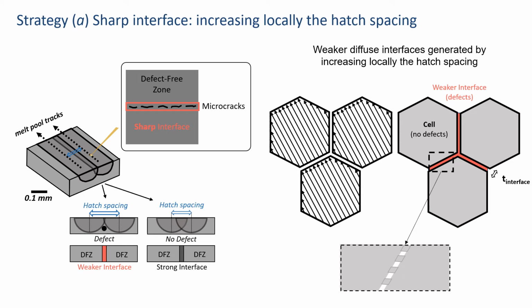And basically there are 2 strategies to do that. The first one is to locally increase the hatch spacing, and this was thought to be a good way to generate sharp interfaces, because it's well known that if you increase the hatch spacing at some point, the melt pool will not overlap correctly anymore, and you will generate a defect, and these defects are organized as microcracks. And the idea here is really to introduce within the laser strategy some areas with locally increased hatch spacing, and what we are hoping to generate is some kind of interface that contains ligaments connecting the matrix so that it's not completely disconnected, but at the same time it generates small microcracks locally.